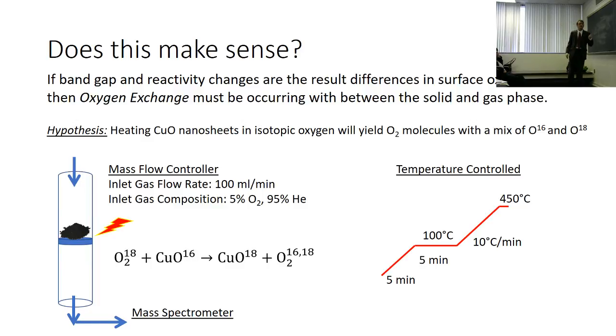So I did something called isotopic TPO, temperature programmed oxidation using O18 oxygen. O18 is an isotope of oxygen, it has a heavier weight, which looks different in the mass spec so you can differentiate it from O16. The only source of O16, normal oxygen, is in the copper oxide nanosheets. The only source of heavy oxygen is in the gas phase. So if I see a molecule in my mass spec that has one of each atom, then I know exchange had to have occurred. It's the only way you get that.